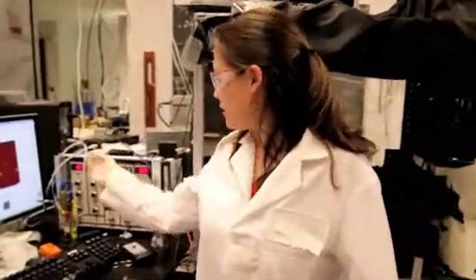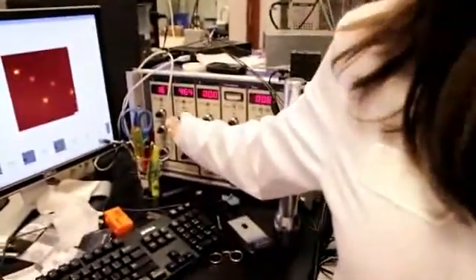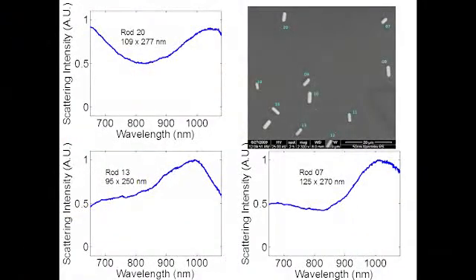Once we have identified the particles that we're interested in characterizing, we can use our nanopositioning stage to move the particle so that we collect a spectrum from only that particle. Here are the scattering spectra of individual nanorods in this area. You can see that they all scatter different wavelengths, and therefore this kind of single particle correlation is extremely important for understanding how tuning the geometric properties affects their plasmonic properties.